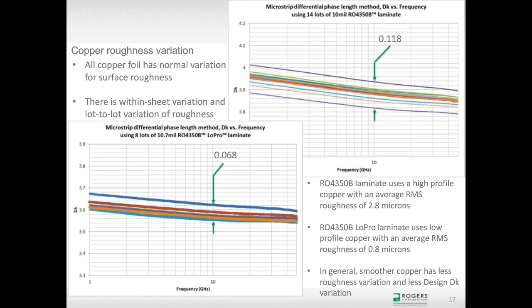And just, again, for the numbers, the surface roughness on the standard RO4350B laminate, 2.8 microns RMS average, and then the LoPro copper that's used on the 4350B LoPro laminate, that's 0.8 microns RMS roughness average. And, of course, also you get the benefit of less insertion loss with smoother copper.